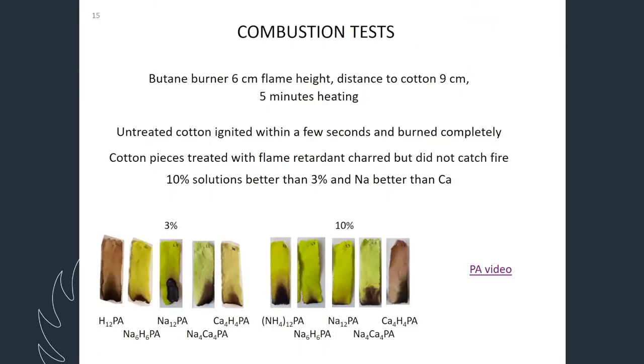So you have seen that phytic acid, the sodium salt, worked quite nicely as a flame retardant. Below we have some pieces of different composition. The left one, 3% solution, is just pure phytic acid, no metal ions. And you can see the ones with the sodium actually worked better. The burning is much less. And when you go to 10%, then it is extremely low. Even when we heat it for 5 minutes, it didn't burn.